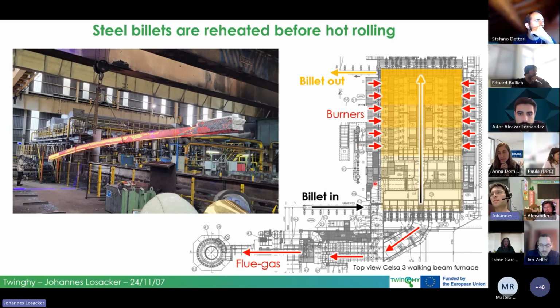This reheating process takes place at Celsa 3 in a so-called walking beam furnace. There are several beams, stationary and walking ones, in this furnace, and they perform a stepping pattern to move the billets through the furnace. Indicated by this black arrow down here, the billets enter the furnace chamber, shown in yellowish in this top view of the furnace. The cold steel billet enters down here, steps through the process going upwards in this figure, and leaves the process after about 3 hours, hot and ready to be hot rolled. This furnace is operated by burners.